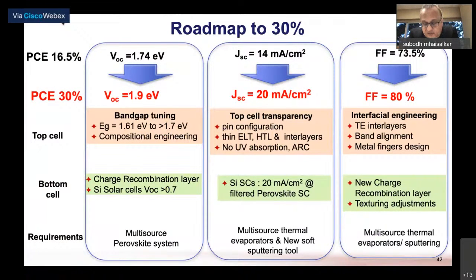What we have completed in the lab so far is, for 4-terminal tandems, we can get efficiencies in the range of 26.5%. And for 2-terminal tandems, we are getting efficiencies in the range of 18 to 20%. Most of our challenge so far has been in matching the performance of the perovskites with the performance of silicon. So the question that we're asking is, what is the roadmap towards 30% perovskite silicon solar cells? The first step is to increase the VOC from about 1.7 to 1.9.